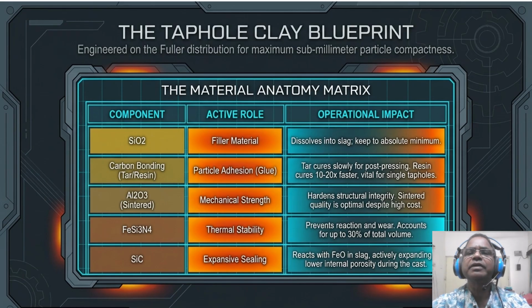And as far as silicon carbide is concerned, silicon carbide is our expansive sealer. It reacts with the FeO in the slag to actively expand and lower internal porosity. The so what is simple. The wrong clay chemistry leads to higher wear rates, which means your taphole diameter increases during the cast, and this turns a controlled extraction into a chaotic torrent, making it impossible to transition from turbulent to laminar flow in the troughs, ultimately risking a granulator explosion downstream.